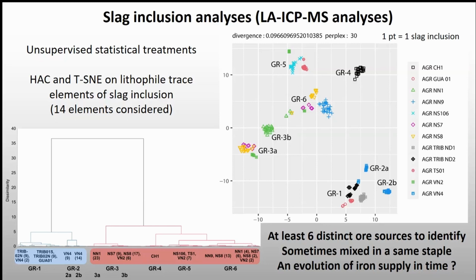So we did not actually explain the patterns so far, but what's interesting is that it's showing that there's a gathering in the same place of iron from different origins, and that's many different origins, and that could then be forged by the smith. And so we can see here with the pink and yellow, but also with the other one, the green one, which is about the same also, and has maybe another provenance too.